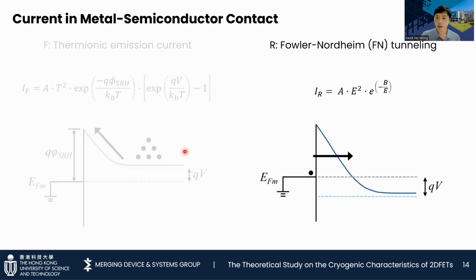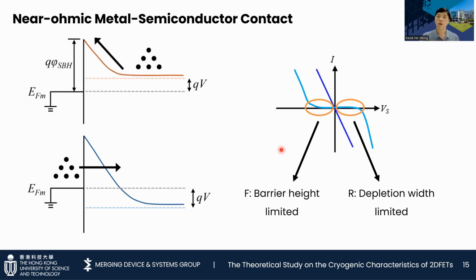But under the reverse bias voltage, FN tunneling is the mechanism responsible for the current flow in the metal-semiconductor junction. When reverse bias is applied, the energy bands of the semiconductor side bend down, causing the depletion width to be thinner. Despite the presence of the potential barrier, the electrons from the metal side tunnel through the barrier and move to the semiconductor side. The reverse current is expressed in the following equation. Therefore, to minimize the contact resistance and achieve ohmic behavior, it is essential to optimize both the thermionic emission and the tunneling transport by minimizing the barrier height and narrowing the depletion width.